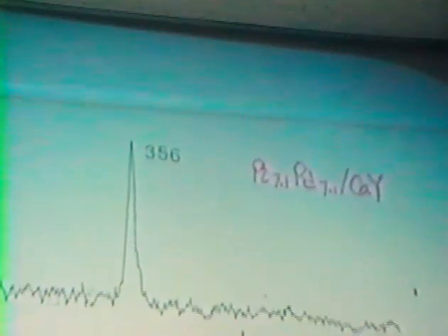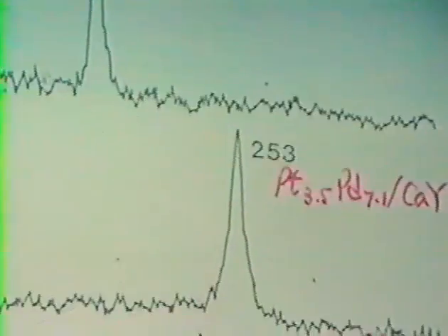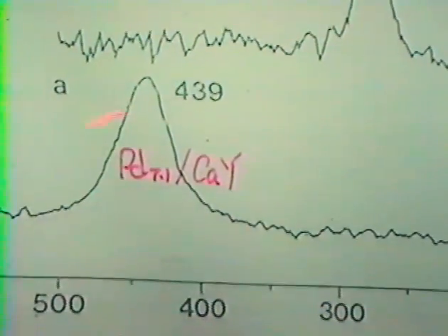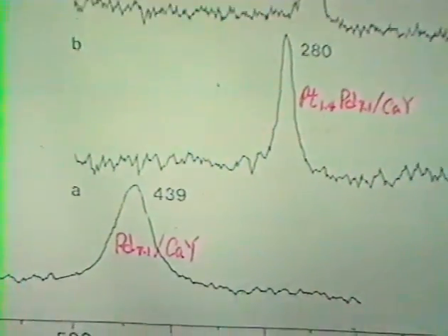And we need to characterize this change by other techniques, because xenon NMR is a relative technique which just shows us some direction of the change, and we don't know what the direction is. And when we added more platinum here, the chemical shift decreased, but not so much. And then when we added further, the chemical shift increases again. So we can imagine that this platinum is covered on the surface of this palladium cluster.